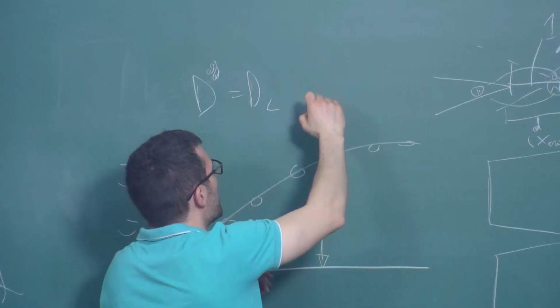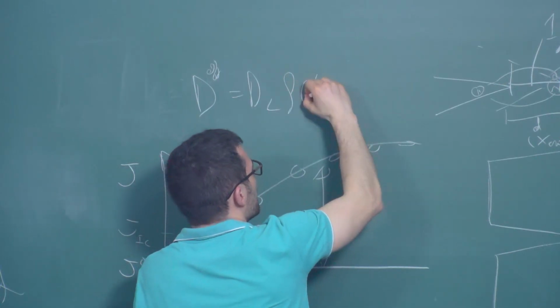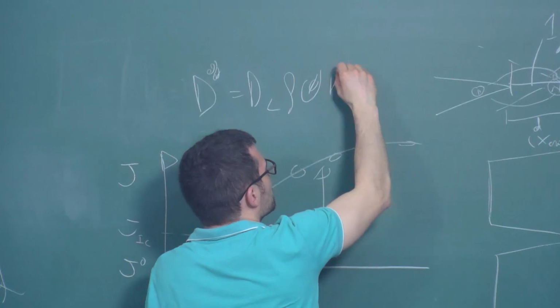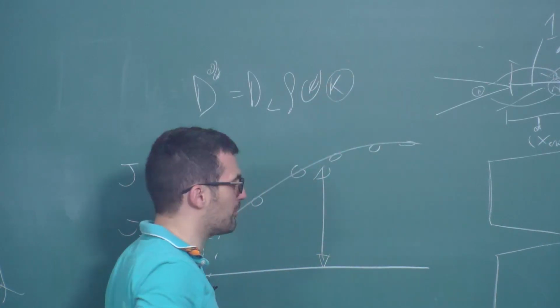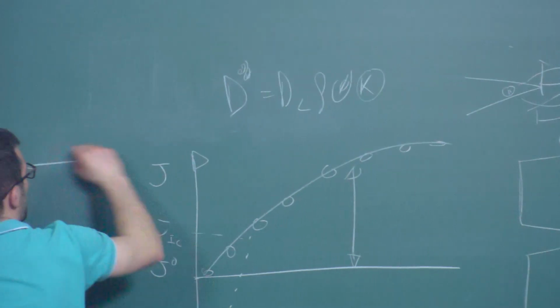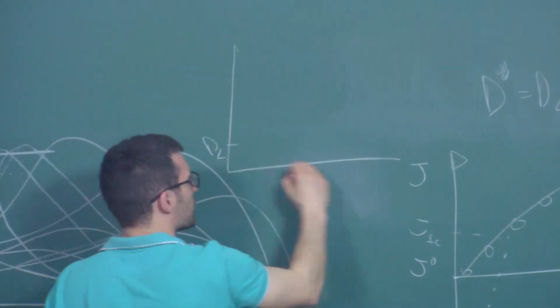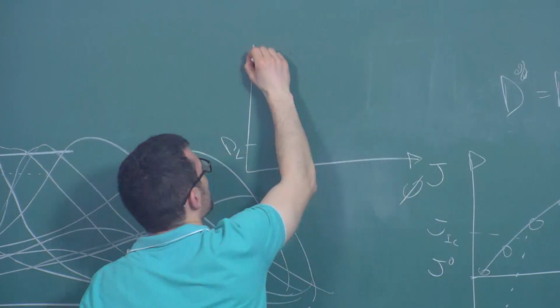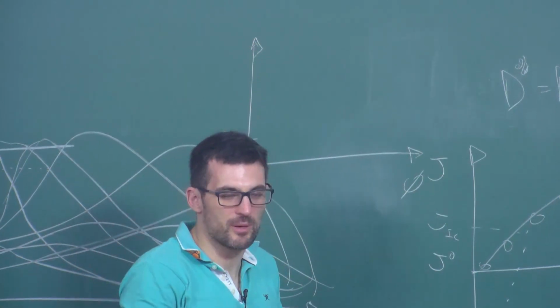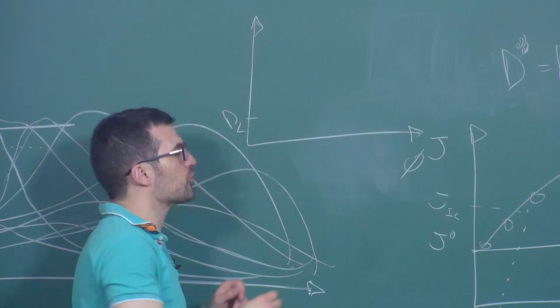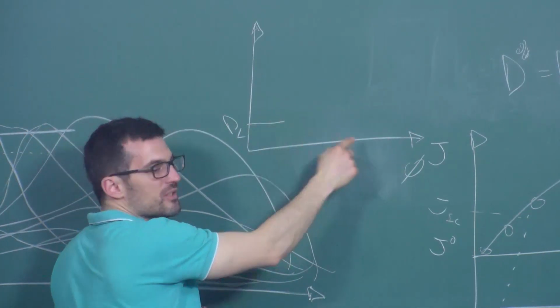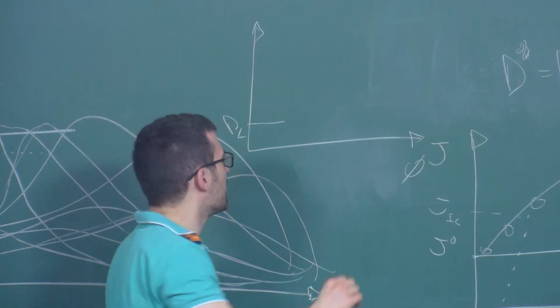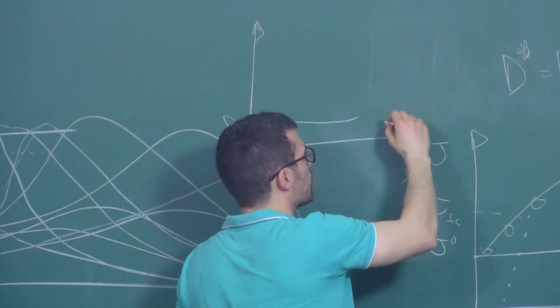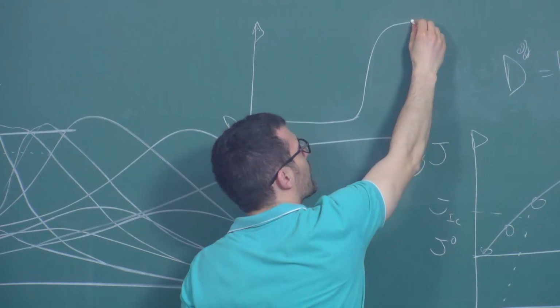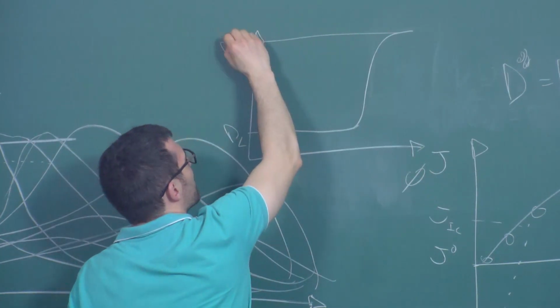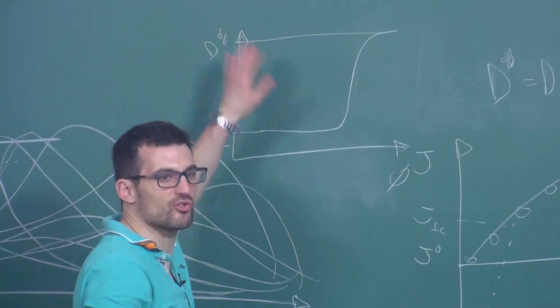It can be any function that you want, but some sort of function of the phase field and some sort of amplification factor. So basically, when you look at diffusivity versus phase field, and this is in the COMSOL Engineering Fracture Mechanics paper that we recently published, this we found to be the most robust. So phase field is low, there's no cracking, your diffusivity is the same, but then as you approach phase field equal to 1, this grows in a quite smooth way to a value that is this effective. It could be 4 orders of magnitude larger.